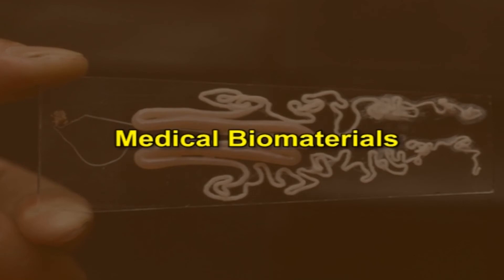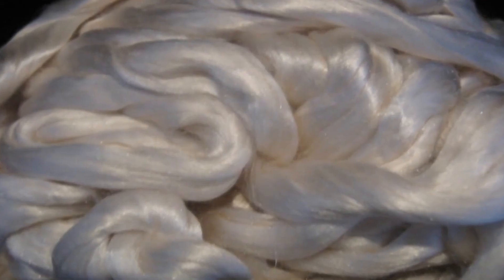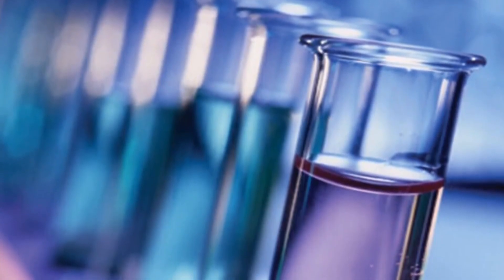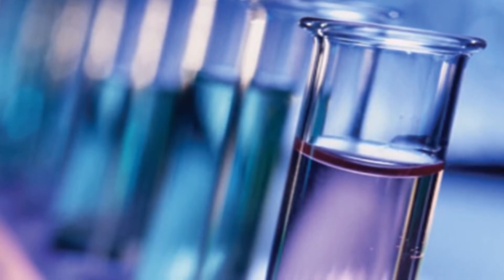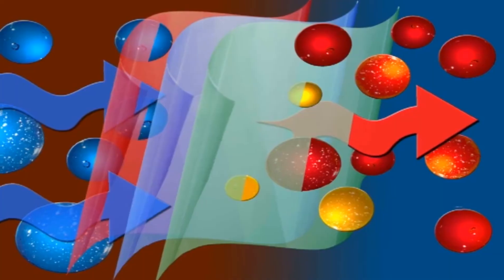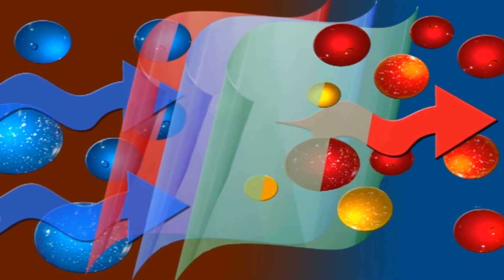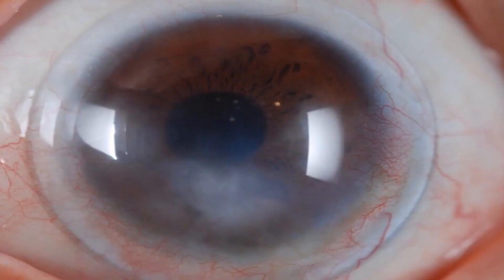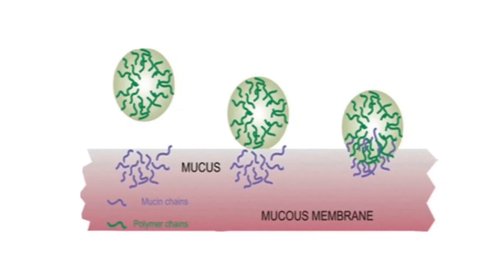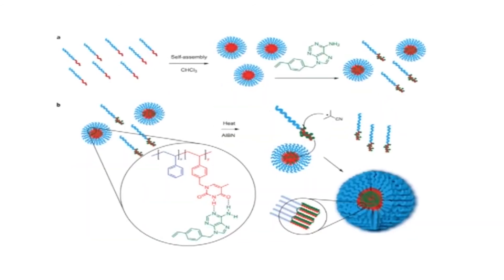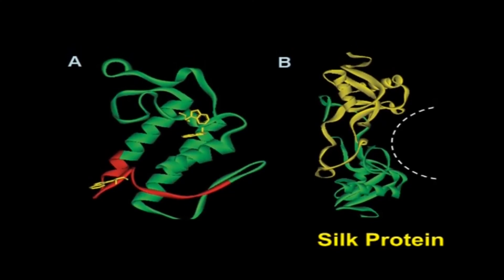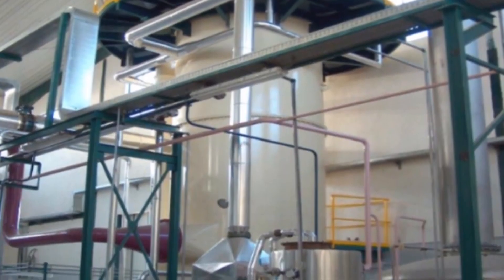Silkworm silk fibers have been the primary silk-like materials used in biomedical applications, particularly as sutures. During decades of use, silk fibers have proven effective in many clinical applications, though some biological responses to the protein have raised questions about biocompatibility. Films made of sericin and fibroin have excellent oxygen permeability and are similar to human cornea in their functional properties, making them candidates for artificial corneas. A novel mucoadhesive polymer has been prepared by template polymerization of acrylic acid in the presence of silk sericin. Silk protein can be made into biomaterials with anticoagulant properties by sulfonation treatment of sericin and fibroin.